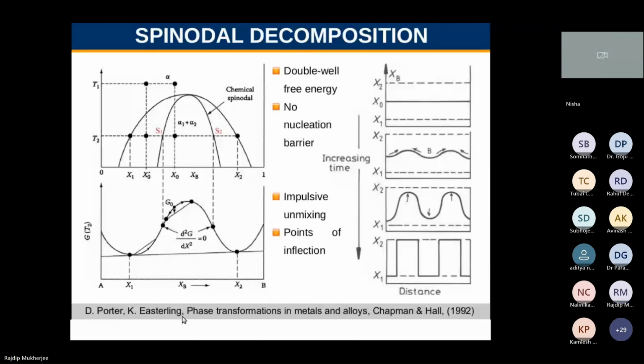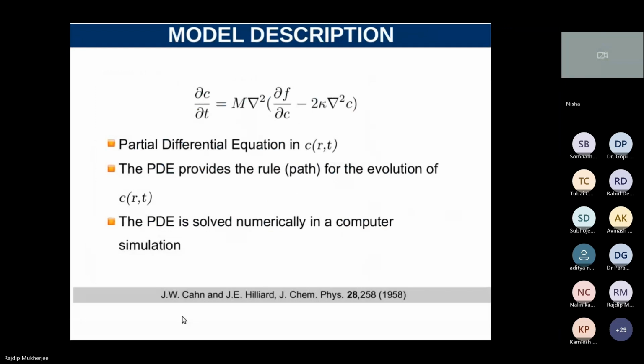Okay. So then this model description that we have already described. This is what we have used, the Cahn-Hilliard type equation, where C is the composition, M is the atomic mobility, which is related to the diffusivity, F is the bulk free energy that I have shown in the previous slide, the double well potential. Kappa is related to the interfacial energy, and the gradient of C is the gradient of the composition. So at the interface, you have a gradient in composition, so it will contribute to the interfacial energy.